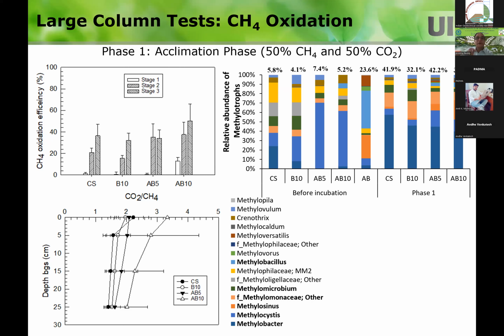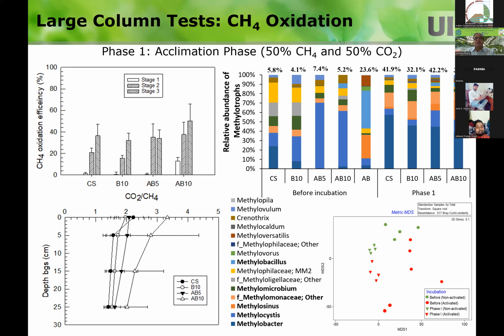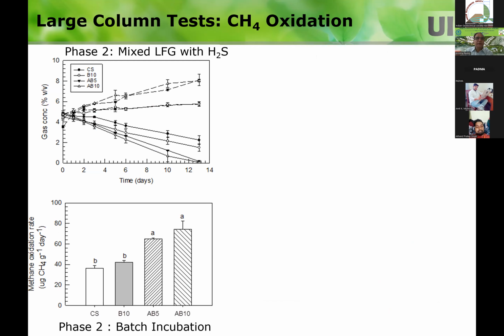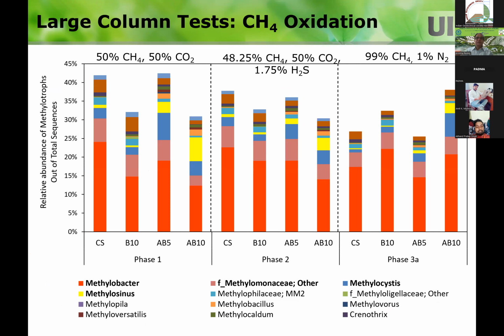Again, you can look at what kind of methanotrophs are there in different columns and how they are changing. See, before incubation, and then phase 1, and again phase 2, phase 3. So in each situation, we know how much is the oxidation and what is the type of methanotrophs that we have. Look at it, in this situation before incubation, we have a very small amount of methanotrophs, but after phase 1, you can see significant amounts of methanotrophs that are generated in the system.